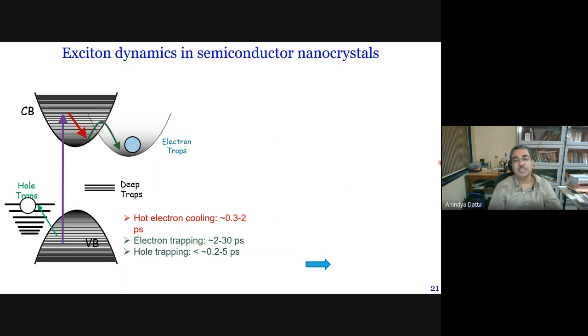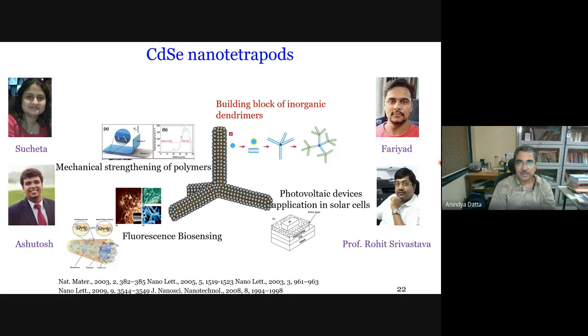Hole can also be trapped. So, there are different defects in the nanocrystal. Crystal has to end somewhere, and that is where we get defects. So, especially at the surface, there are plenty of defects depending on their chemical nature. They can capture electron or they can capture hole. So this hole trapping is again a very fast process. And then we can have shallow trapping, deep trapping, a lot of things. We can have something called Auger recombination, where an electron can just pass its energy to another one while recombining with a hole, and the second electron can be promoted.